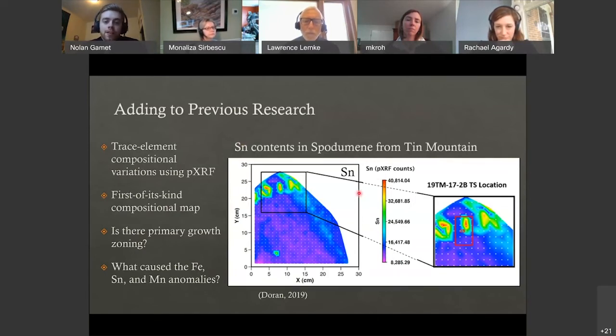But they still had two questions remaining. They tried to determine if the primary growth of spodumene was a result of a solid solution in the crystal, and then they tried to determine the causes of iron, tin, and manganese anomalies, where they came from. To do this, we selected a thin section location on the sample TM17 that included one of these anomalies, along with the other cooler portions of the zone.